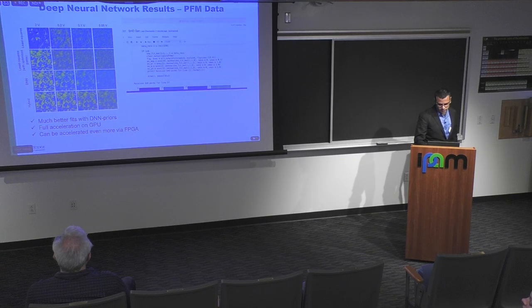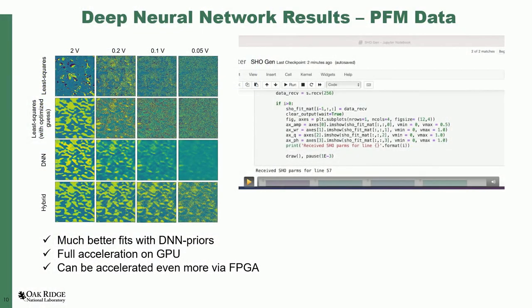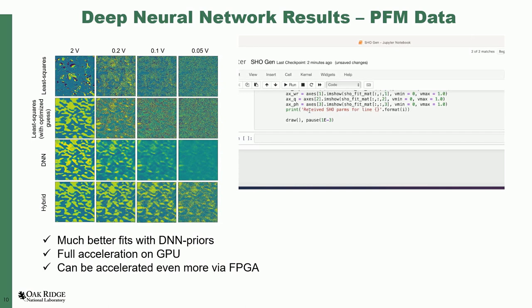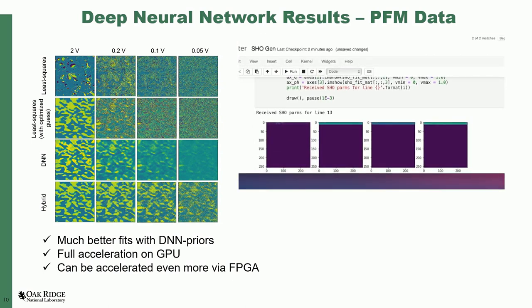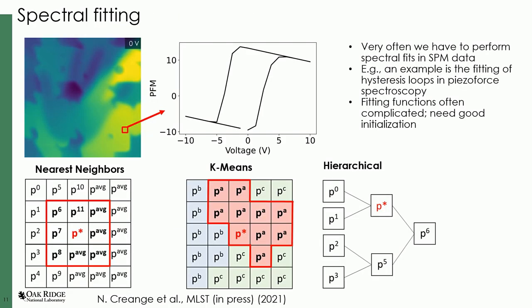And the other thing here is that we've set it up so that we can run this on a cluster, and so we can get fits line by line as it comes through the microscope. At every line, this is sent to a GPU server. It does the inference, it does the fit, and it sends the fit back, and then we plot it in real time. So this is what you see when we have this inline on the microscope. We can do better than this, of course.